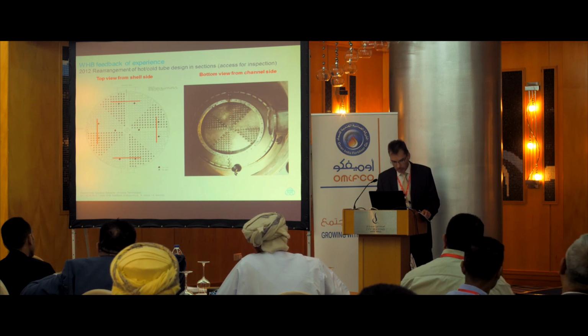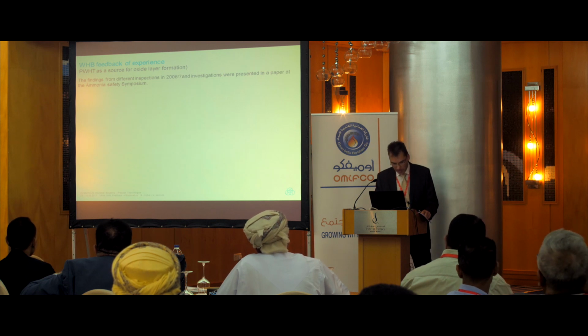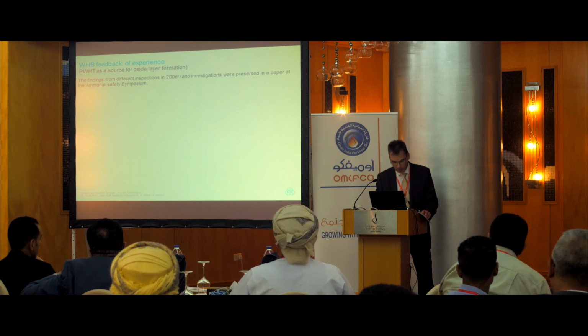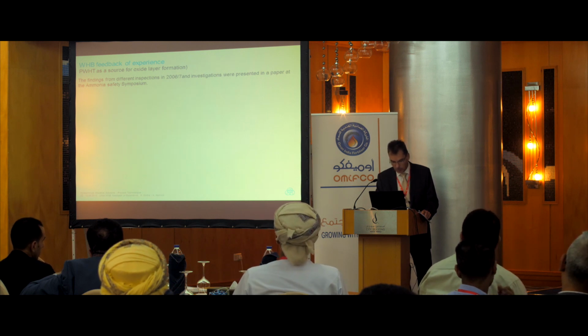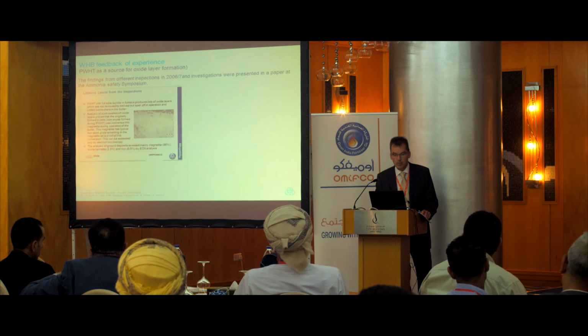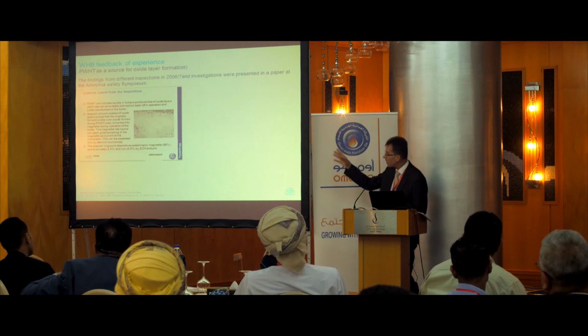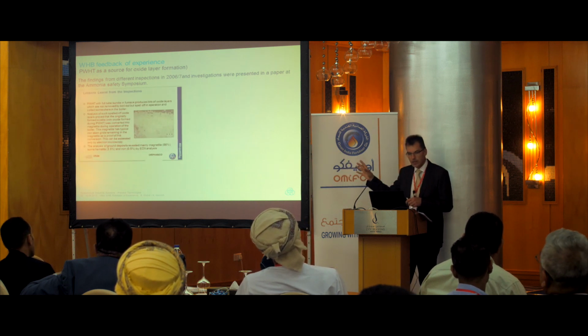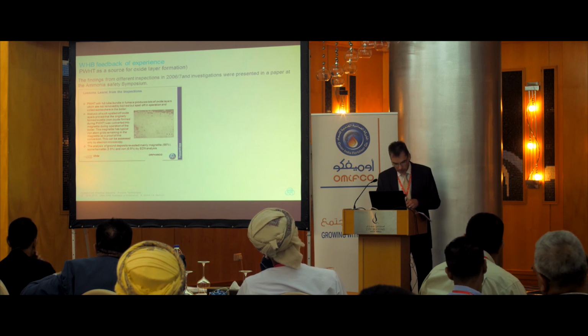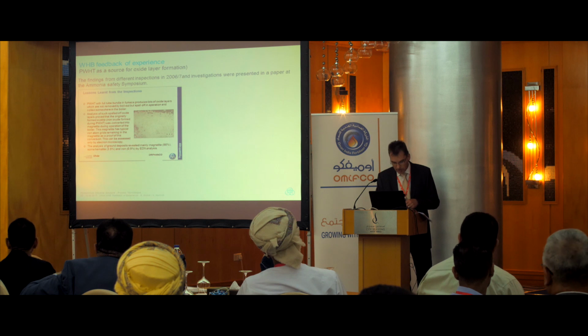But there was another modification we did. From the material samples of spalled-off oxide layers, a clear origin from the post-weld heat treatment could be proven by scanning electron microscopy. Here's just a short description. I will not read it down. What you find when you do the scanning electron microscopy, but the forming of magnetite is shown on the slide on the left side. You see how it looks like normally here on the left side.